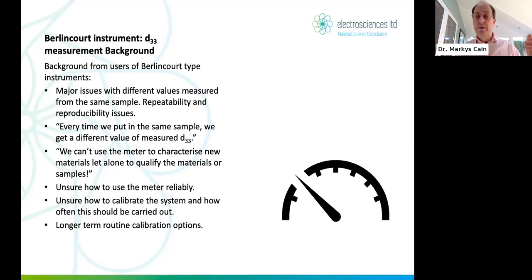This Berlincourt, we're applying a sinusoidal stress in one direction, and measuring a charge. That's the measurement. And Don Berlincourt basically developed it. There are all sorts of issues from all sorts of different companies and universities and research groups, major issues with different values measured from the same sample. So repeatability and between-labs reproducibility issues, major issues.